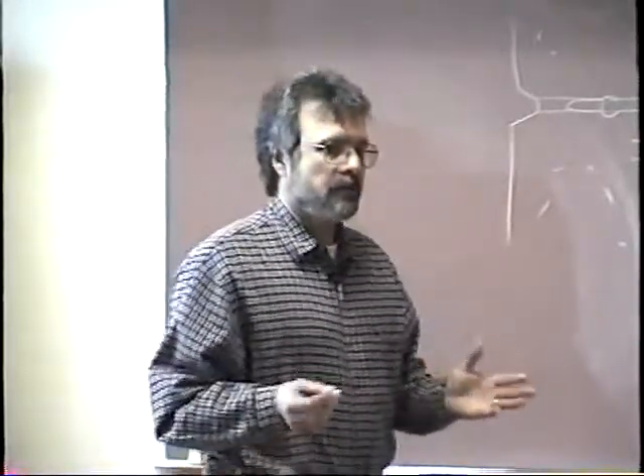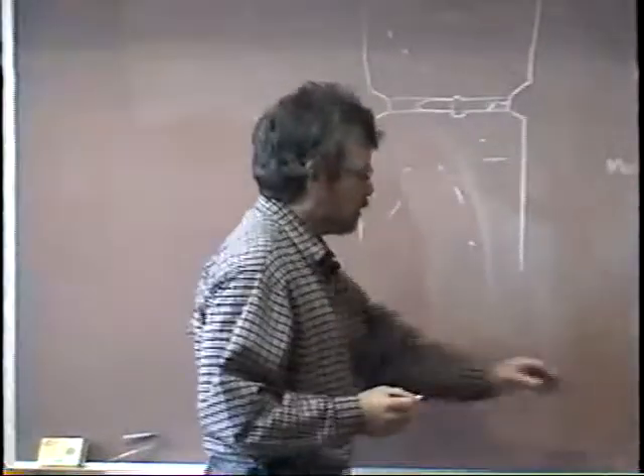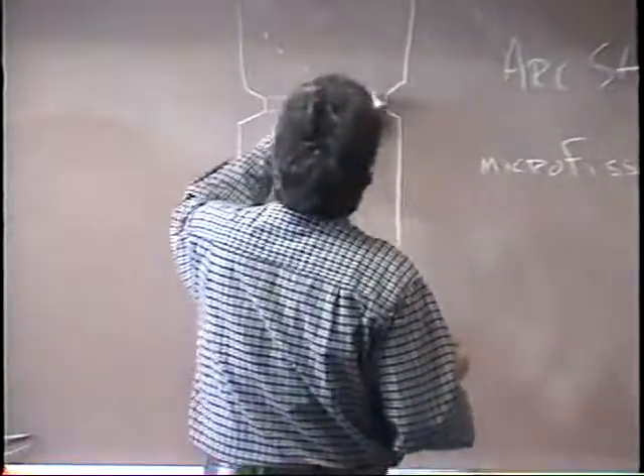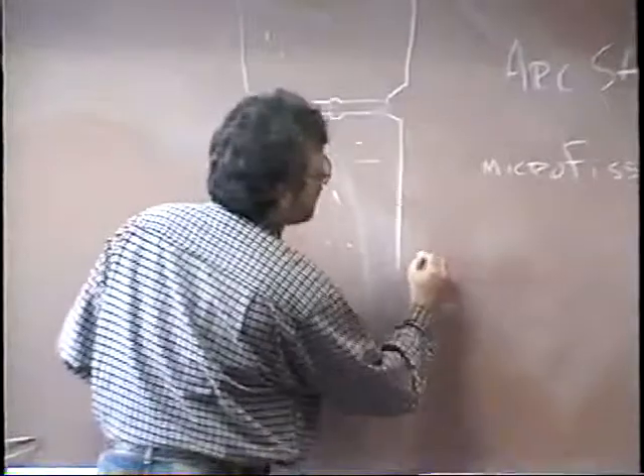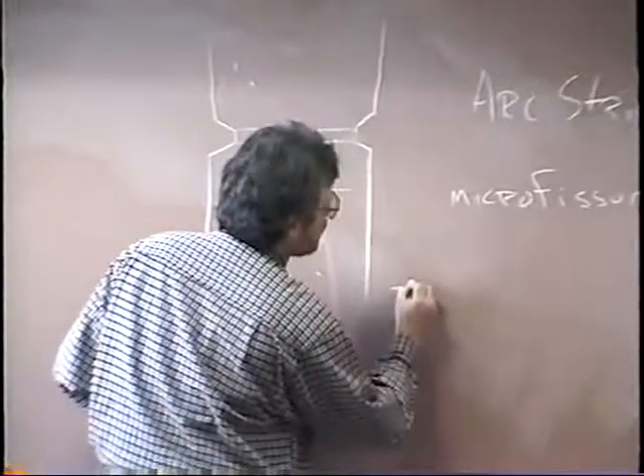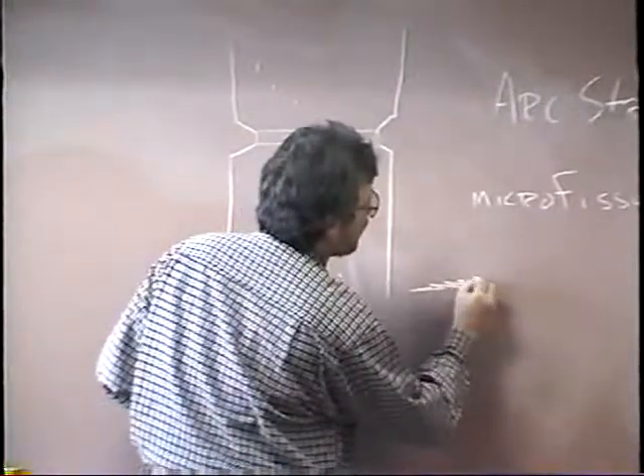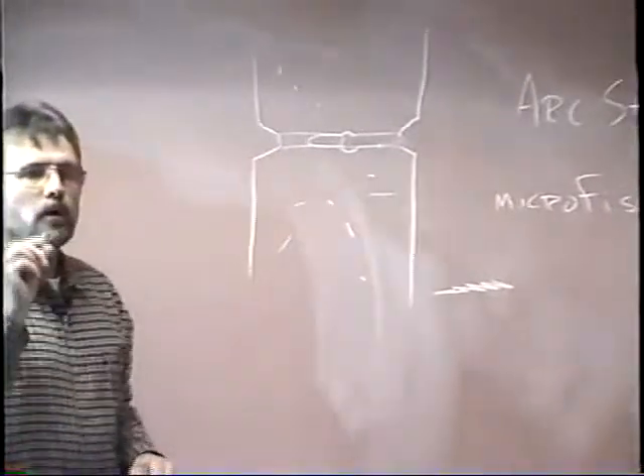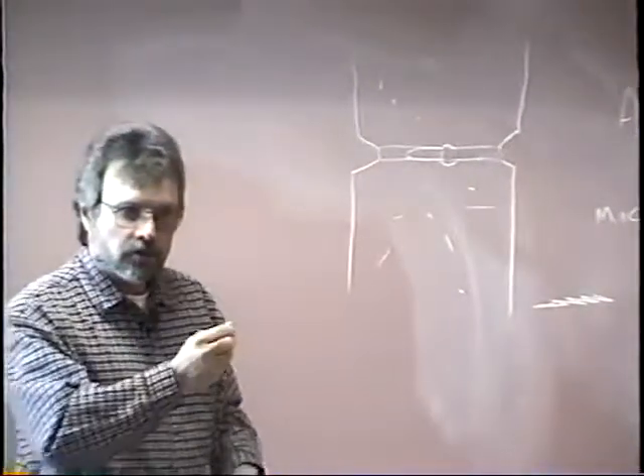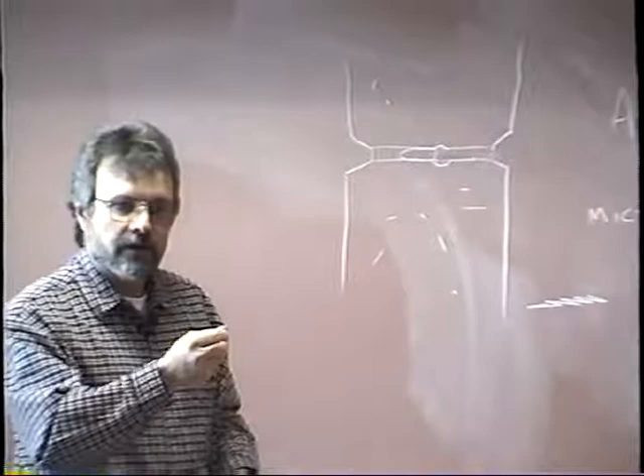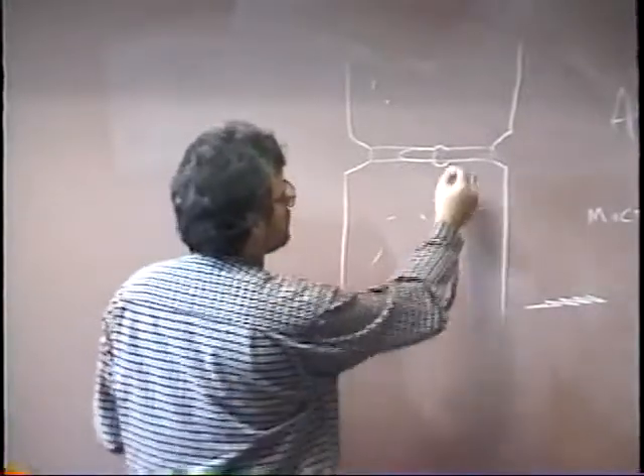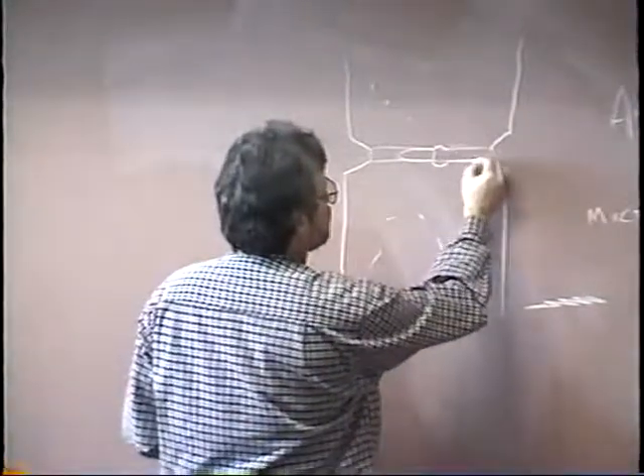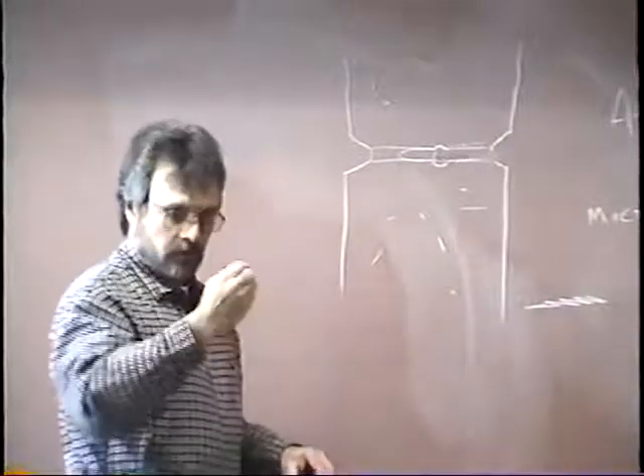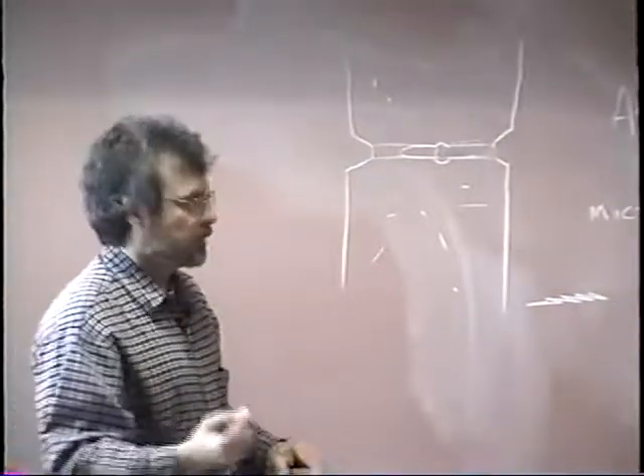Now this guy prefers to use a whip, which is fine. But if you read your entire text there, he's talking about a whip that is out back, out back, out back, not more than 1.5 diameters of the welding electrode. So it's more of an oscillation, which is fine. When you use this oscillation, what you're doing is you're preheating that land as you're going along so that you get better penetration. And that's a perfectly fine technique.